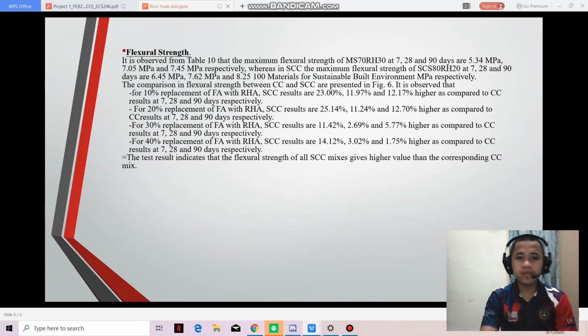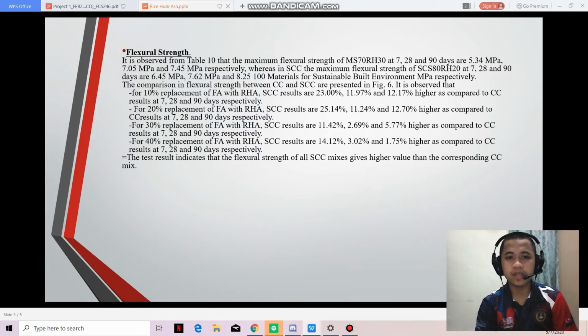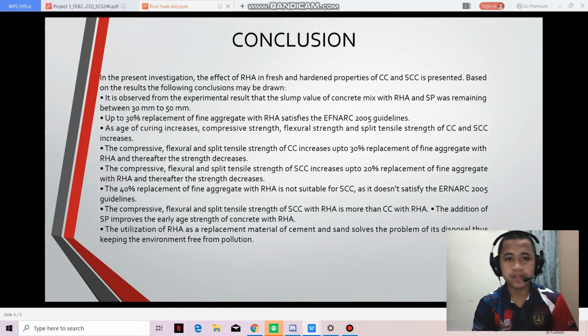The flexural strength, the same thing. First we observe the flexural strength and we get this one, and for 10%, 23, 11.95 and also 12.17, 20%, 25.14, 11.24 and also 12.70, and for 30% is 11.42, 2.69 and 5.77. And for 40%, 14.12%, 3.02% and also 1.75%. It's all for 7, 28 and 90 days.